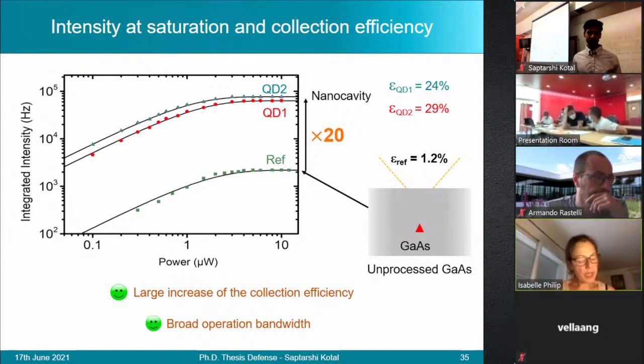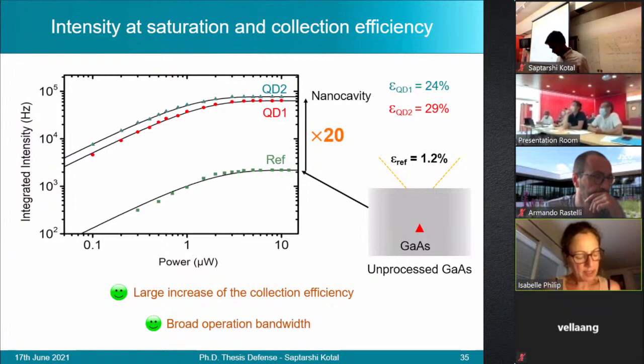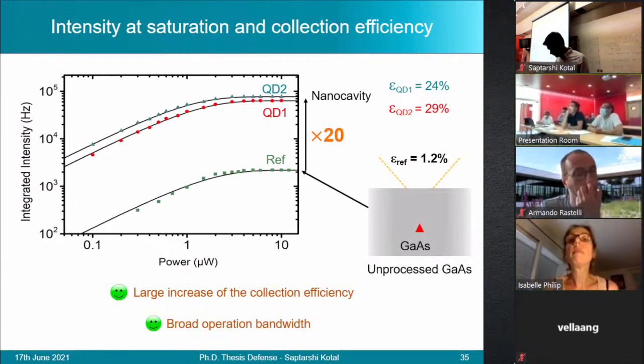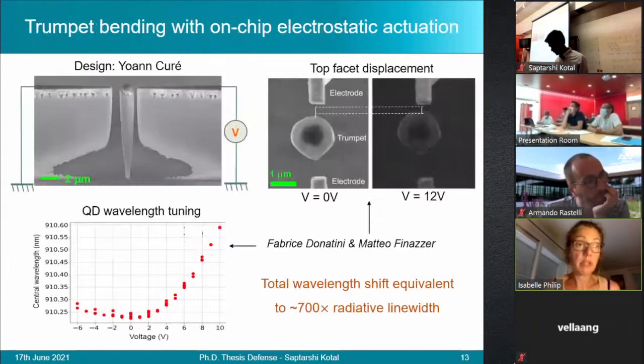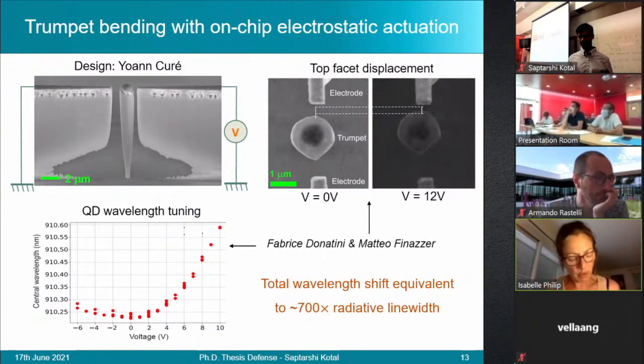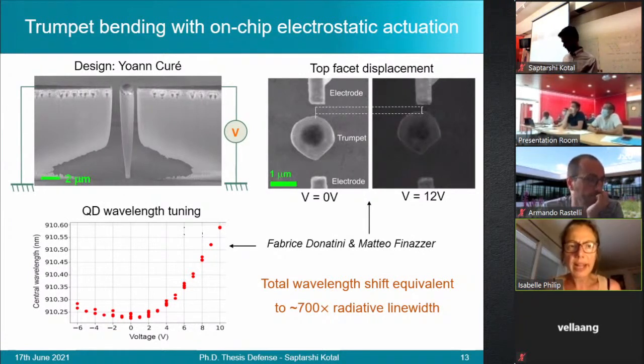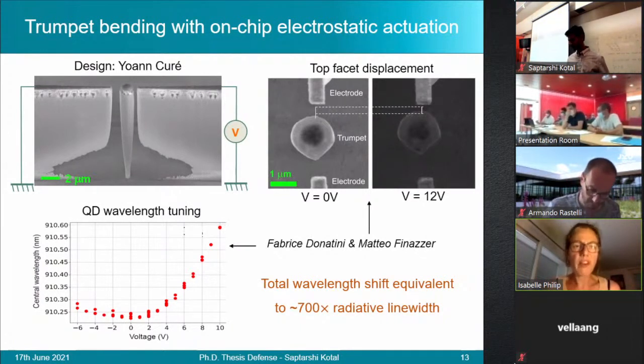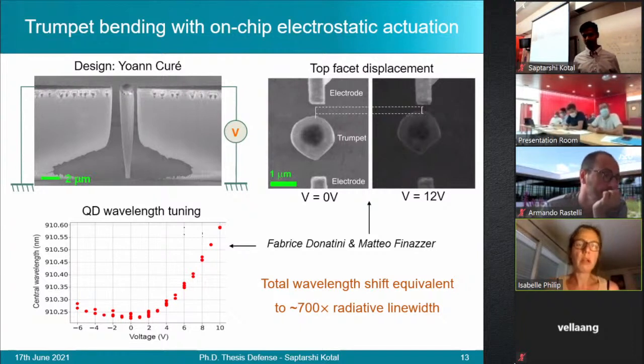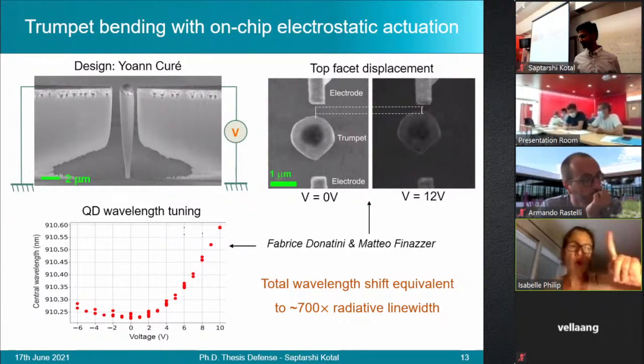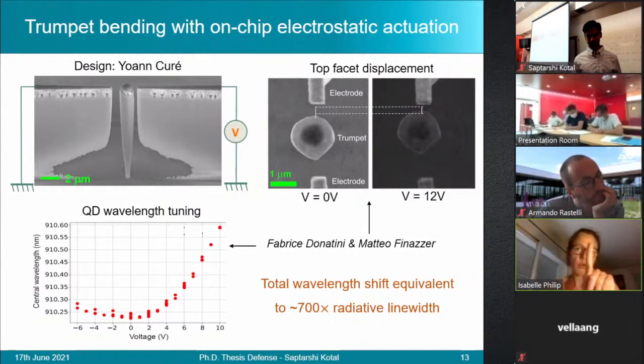Okay. What you showed us on slide 14, I think, is that you have a very strong shift. Yes. About 700 times the line width of the dot, which is already very impressive. Yet, if we translate that into milli-electron volts, if I'm not wrong, it is something like a 0.2 milli-electron volt shift, and your prediction is about 1.5 milli-electron volts. Is it due to the fact that the calculations are done for a dot which is really at the edge, whereas you are not completely at the edge in that case? And is it possible to estimate the dot position laterally, to check that the tuning is smaller because you are closer to the center, which would explain why your shift is smaller than the one you predict?